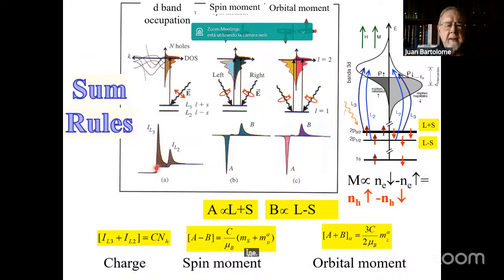It would not be so important unless we now mention the so-called sum rules. The sum rules have given the potential to this technique in magnetism. That's why it is so important from then on. We deal now with the integration of the absorption signal once we have taken out the contribution of the transitions to the continuum. So this area is proportional to the number of holes, which allows us to normalize whatever we observe per atom. So we are always getting information per atom on the average that has been measured.